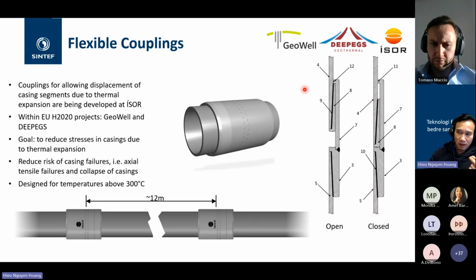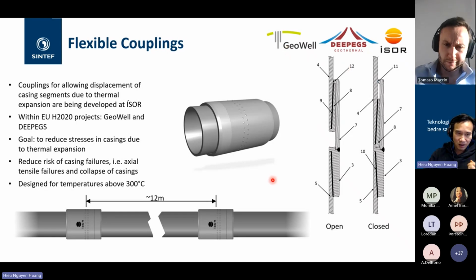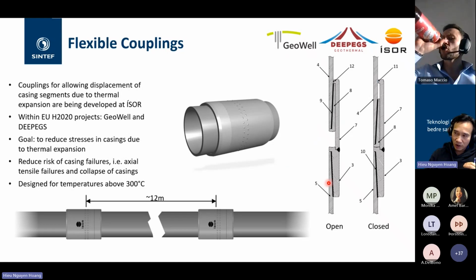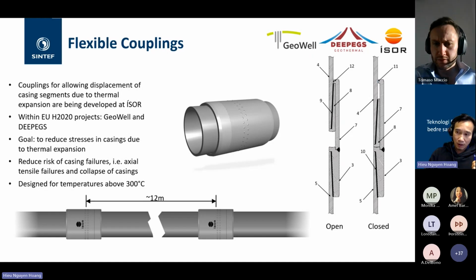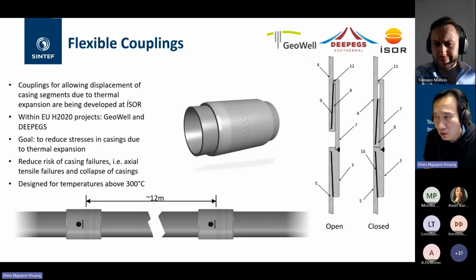It represents a breakthrough technology addressing the thermal expansions. It was developed mainly in the Horizon 2020 project, GeoWell, and these couplings allow the casing segments to move in axial directions in order to reduce thermal stress and minimize the risk of failure, like casing tension and collapse. And this coupling can be designed to operate at high temperature, about 300 Celsius or even higher. And we believe that this technology is a game changer for future geothermal well integrity as a whole.